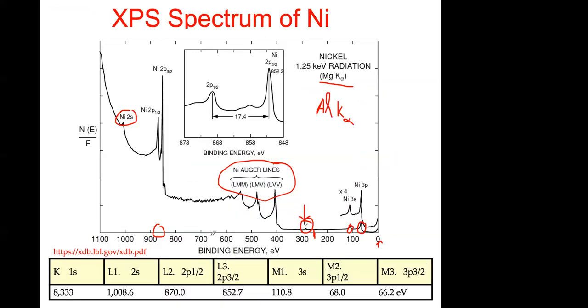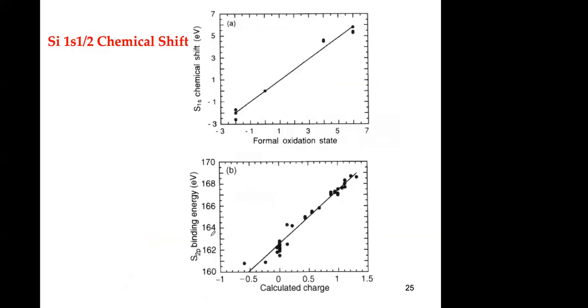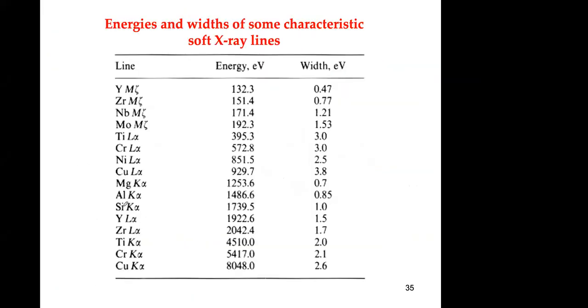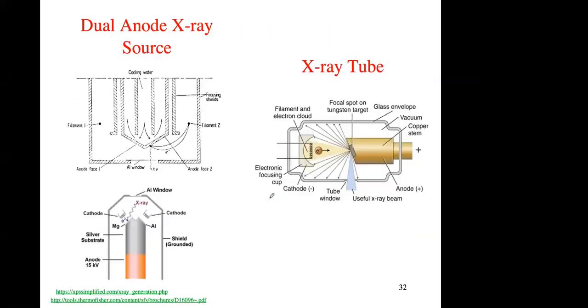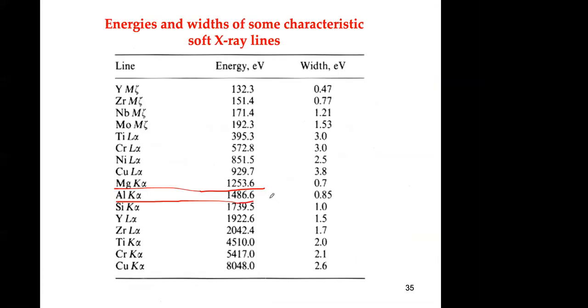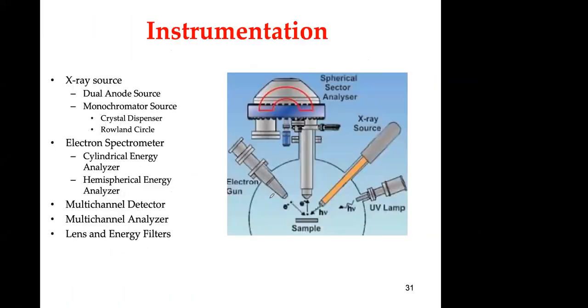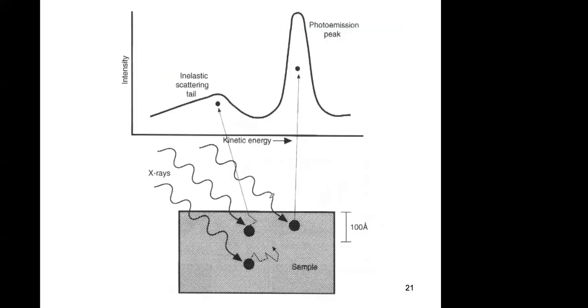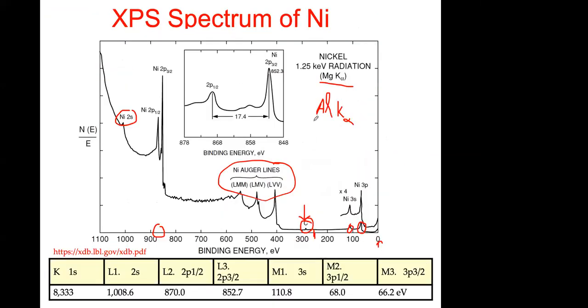Aluminum, I have the values back later. Let's see. Let me go ahead on time. For example, aluminum is 1,486 electron volts, and magnesium is 1,253. So there's a difference of like 200 electron volts. Aluminum is higher, 200 electron volts higher. So if you look at this peak, and this is with magnesium. If you go to aluminum, what do you think will happen to the Auger lines? In what direction will they move? Somebody can tell me?